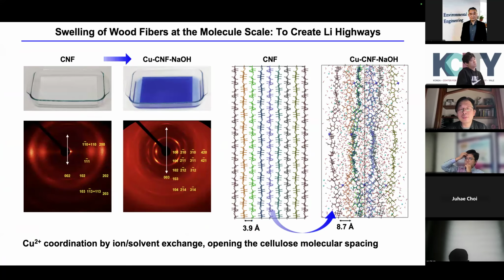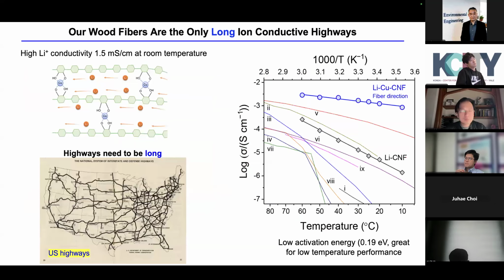You take the fibers, you almost use the kimchi process. You soak it for about 3 weeks, and the copper ion gets into the molecular chains, and then you put the lithium ion into the molecular chains. Now you can transport ions. We get a conductivity up to 1.5 millisiemens per centimeter at room temperature. Of course, it's going to be even higher at a higher temperature.